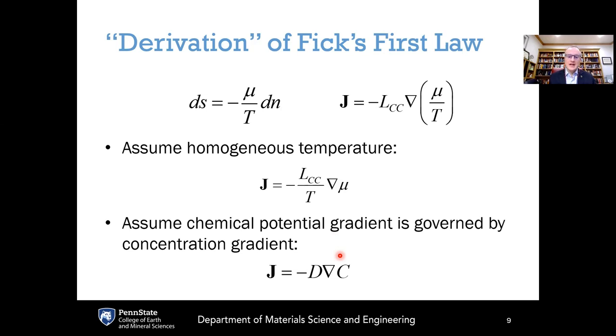Fick's first law is based on the assumption that the only driving force for diffusion is inhomogeneities in concentration. So it's the gradient of the concentration profile. And if you take whatever constant of proportionality is needed to go from the gradient of the chemical potential to the gradient of the concentration, lump it together with our kinetic coefficient and our inverse temperature, then that is declared to be the diffusivity D, also known as the diffusion coefficient.